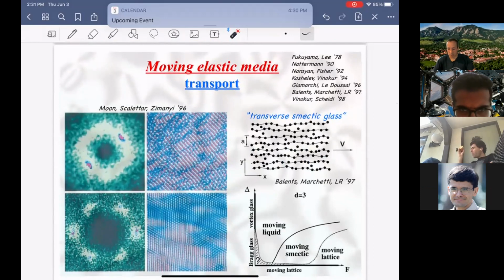In particular, one can imagine, and in fact this was observed in numerics, and we studied this with Leo Balents and Cristina Marchetti in '97, but a problem that was first posed by a variety of people, namely what happens to the Bragg glass or vortex glass, which shows 6 peaks, which may be broadened by disorder. These are reciprocal lattice peaks, Lorentzian-like peaks. What happens to them when this Bragg glass or vortex glass starts moving at high velocities? And what we predicted, and in fact was observed numerically, is that it transitions to what we call a transverse smectic state, where you get layered structure, where there's still some periodicity in the direction transverse to the direction of motion, but there's no periodicity along the direction of motion.